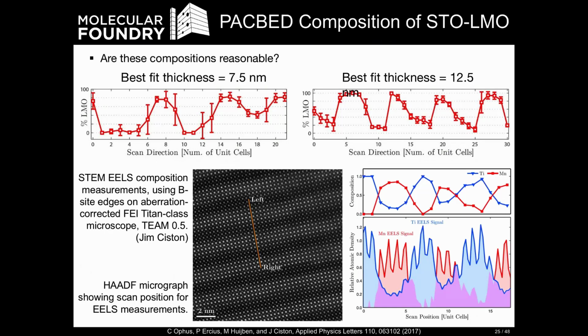But we have all this information here. And sometimes you can't actually do a simulation because you don't necessarily know what you're looking at in detail, or you want to vary many different measurement vectors: polarization, thickness, sample tilt, aberrations, probe size, lots of different parameters. So if you don't want to do the simulation, you can also dive into the data directly to get some information. One of the first easiest experiments we did is just virtual dark field imaging, and I'm going to show some examples from that now.